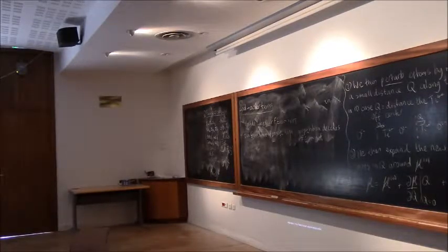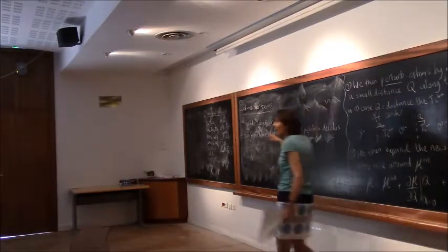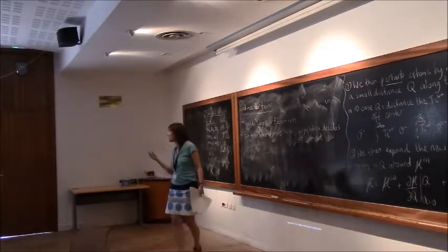Okay, so this term is energy raising. Let's think about what this means. Here, we're taking the expectation value of the second derivative of the Hamiltonian. So, if you like, the curvature of the energy as a function of displacement. As I push my atoms together, they're following some energy well, but I'm not letting my wave functions move. These are my zeroth order wave functions. My electrons are not allowed to adjust to the fact I've pushed the titanium towards the oxygen. And so we know from the variational principle that's got to increase the energy.